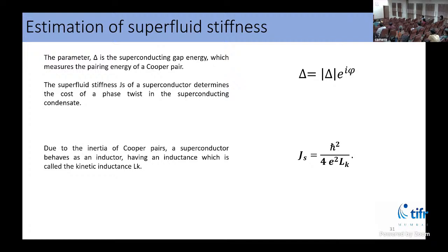Maybe a very naive question, but are there any observable effects if we apply a magnetic field perpendicular to the plane of the trilayer graphene system? Yes. So basically, this particular superconductor does not like magnetic field like any other superconductor. Now, the range at which this superconductor changes to a normal state while I apply perpendicular magnetic field is much lower. It changes at something like 300 millitesla, 0.3 Tesla. Whereas in plane field, I am able to go to much higher values. Even like I showed you, I see some sort of hysteresis even with the application of out of plane magnetic field, but they are not as prominent as I see them with in plane magnetic field.